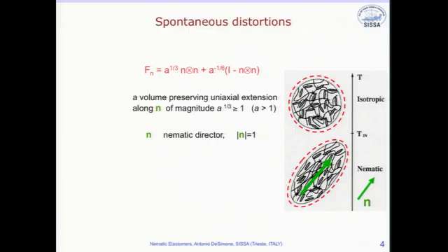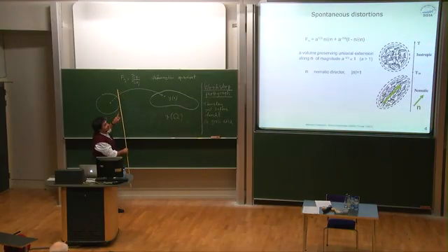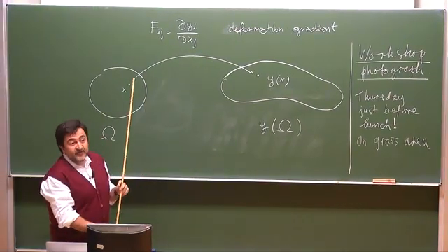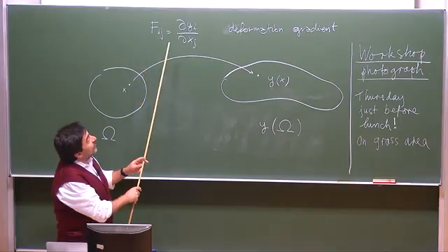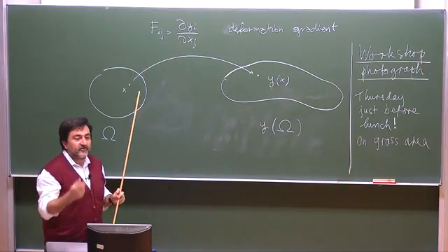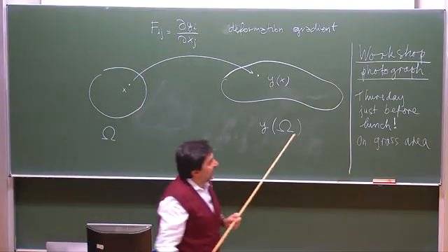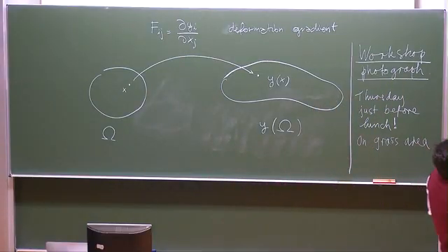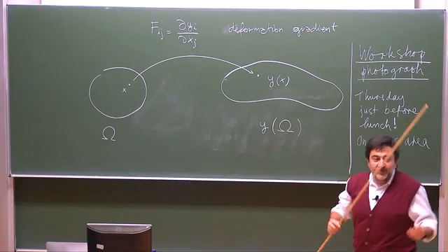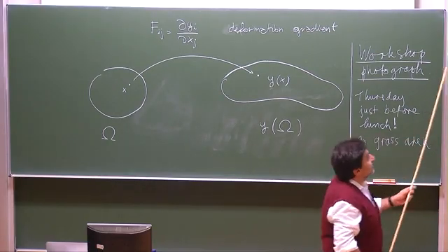Here it is in matrix notation. So here in the background is what I'm going to do. So continuum mechanics, there's a map that tells you the deformed configuration. The key quantity is the deformation gradient. So the ij component is the partial derivative with respect to xj of the ith component of the map. Okay? And there is a special value of that deformation gradient, which is the spontaneous distortion. And here it is. So this is the number. For historical reasons, it's not a, but a to the 1/3. Let me not comment on this.